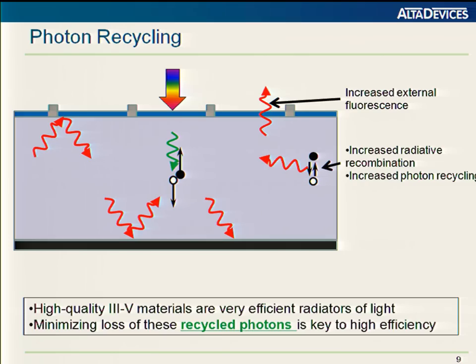We're now not wasting so many to the thick crystal of the cell, and if the semiconductor material is of significantly high quality and the reflector is of sufficiently high quality, you can have very efficient recycling of these photons. That means a recombination event in this device doesn't have to be seen as a loss anymore, because you'll have the recombination event, a photon is generated, that photon is absorbed. The carriers may or may not make it to the junction. If they don't, then they recombine and emit another photon. That has the effect of increasing the effective lifetime of carriers.